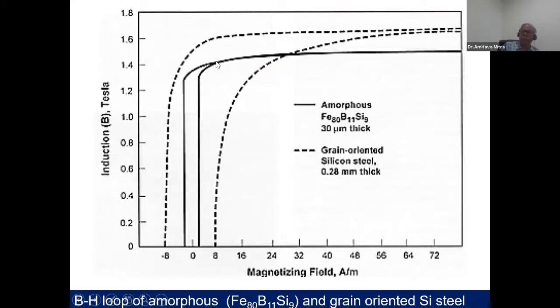But what we can get in this case is around 1.4, but we can say there is an abnormal decrease in the area of the hysteresis loop.